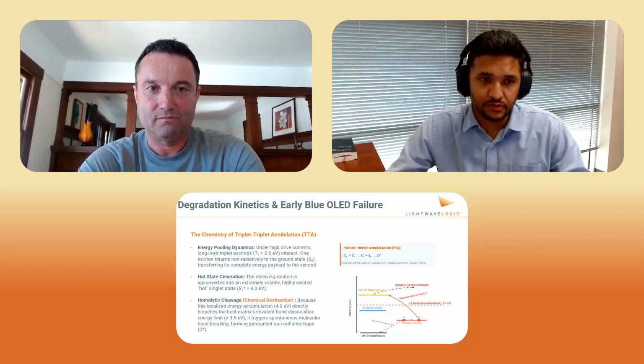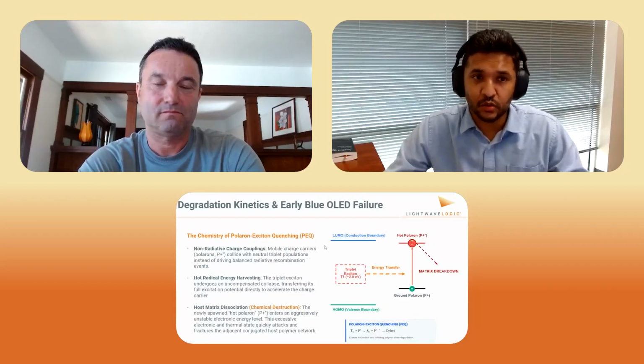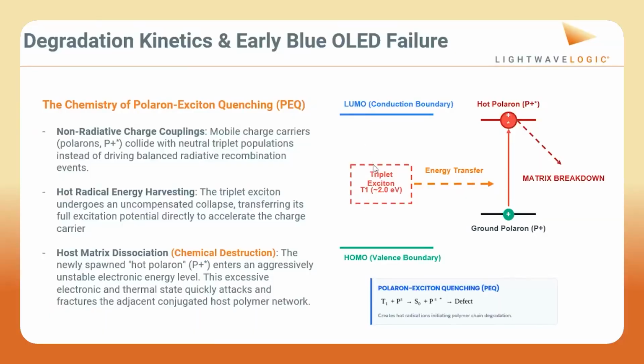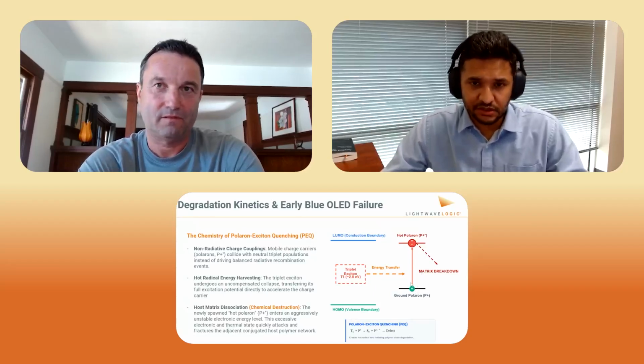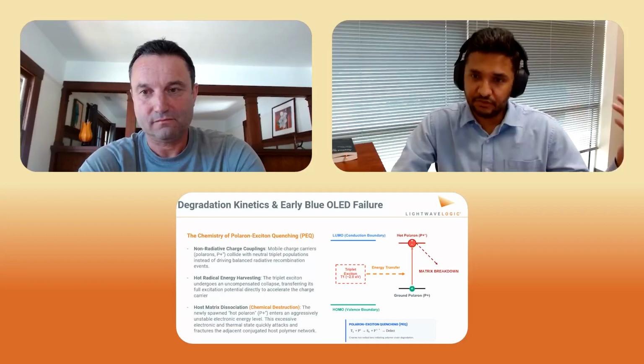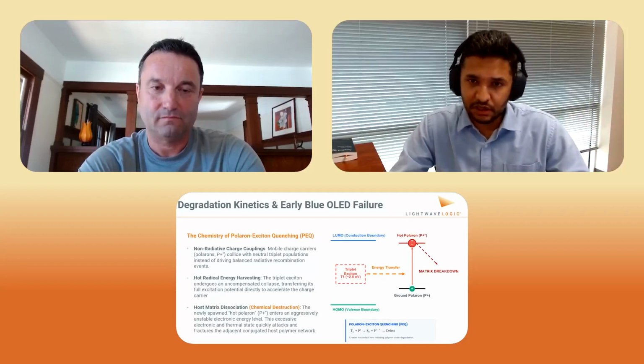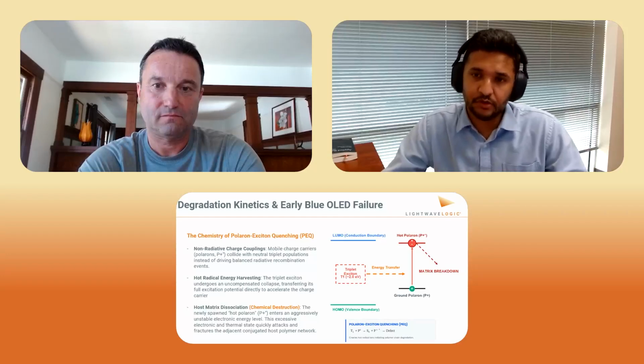There was another fail mode called polaron exciton quenching. It is very similar to what happened with triplet excitons, but now this triplet actually attacks the host polymer in which the OLEDs were prepared. It's basically a similar thing where you attack a host polymer molecule, a ground polaron, where it gets to an excited hot polaron, and it has enough energy to break the chemical bonds of the host polymer. The way they found a solution for it was just a little bit different. They engineered their host polymer to have a really high band gap, and that high band gap allowed them to never break because of hot bonds.